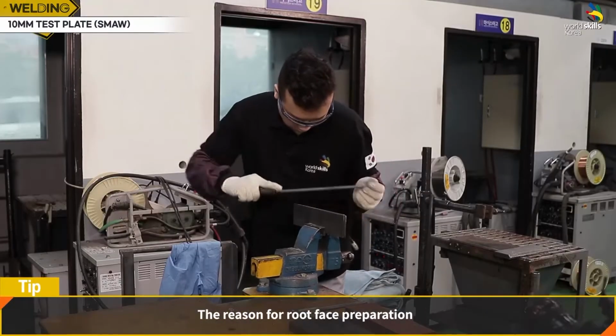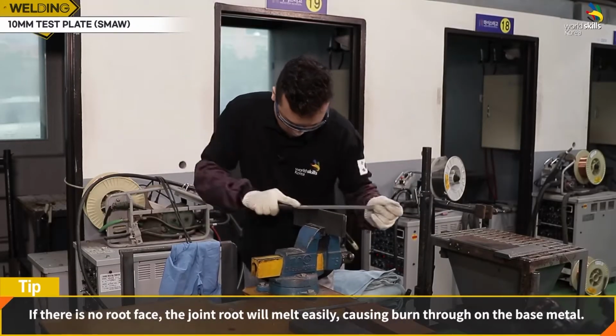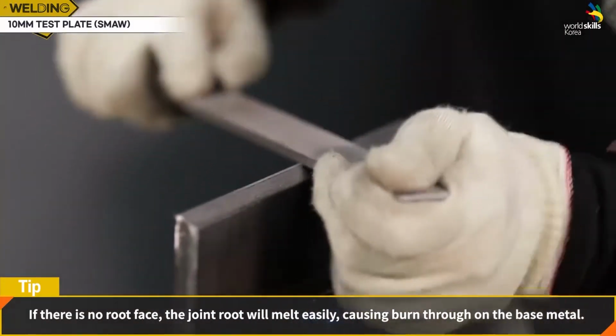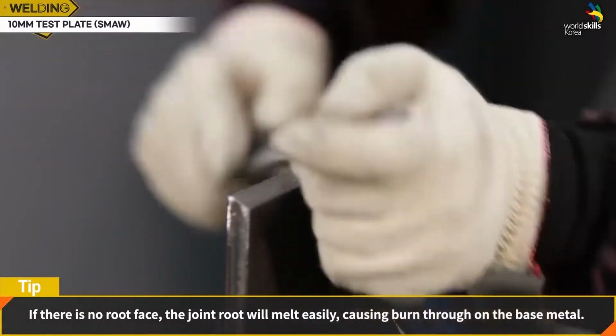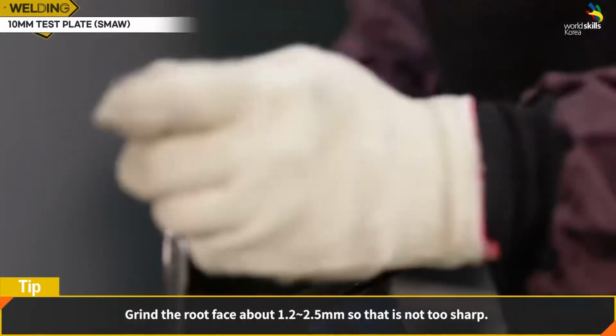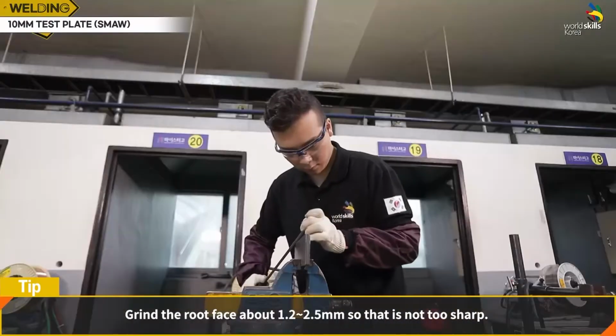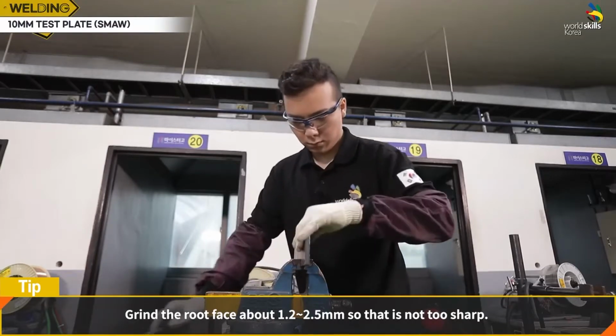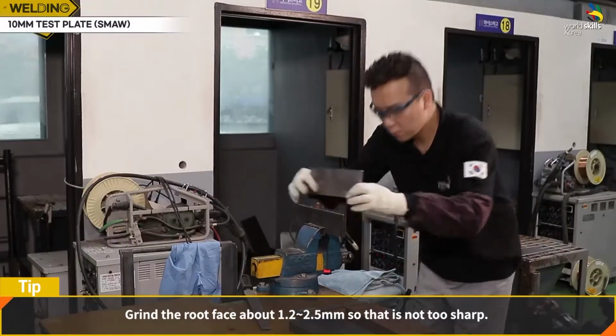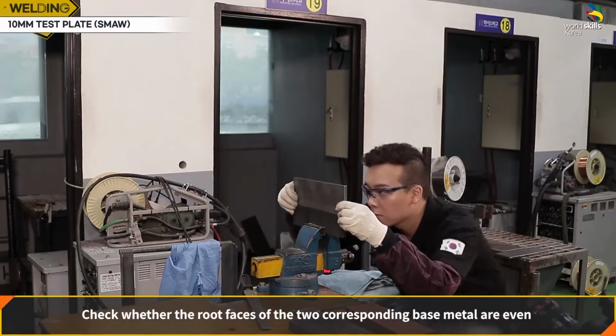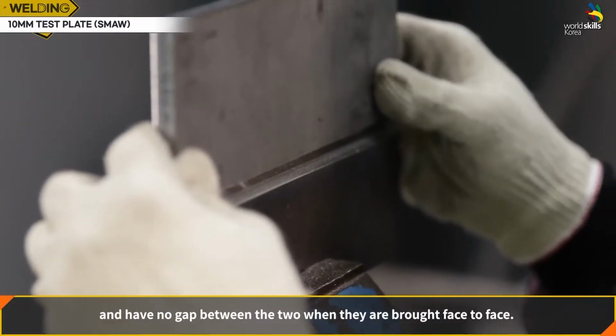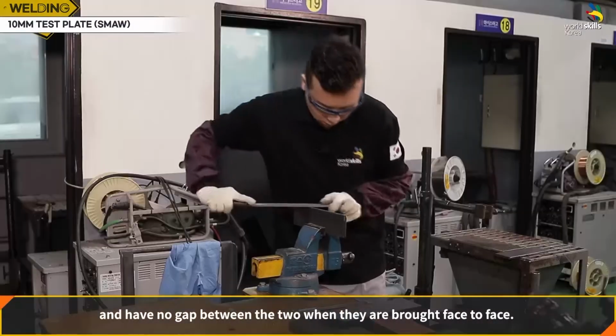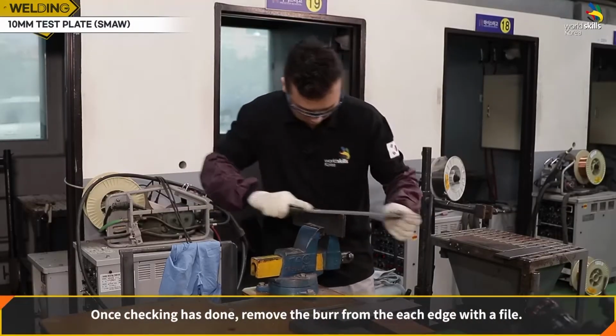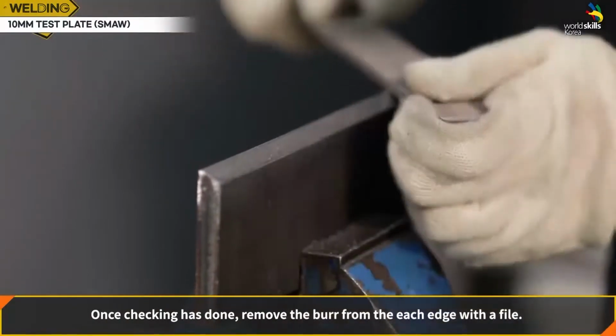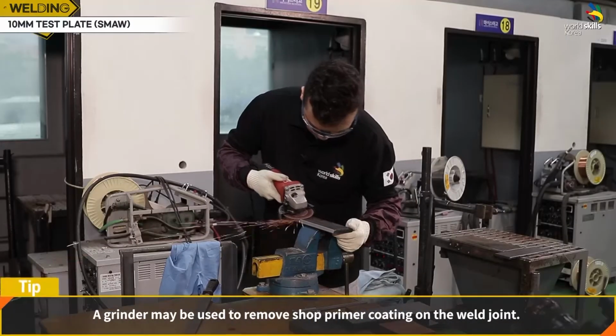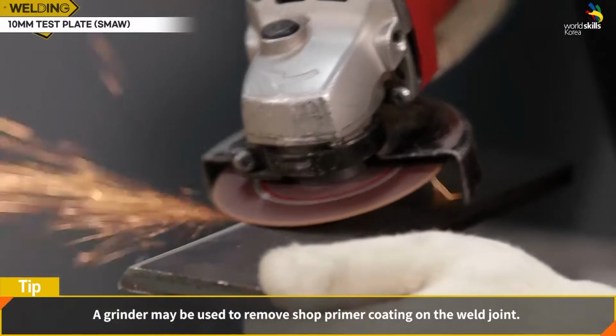The reason for root face preparation: if there is no root face, the joint root will melt easily, causing burn-through on the base material. Grind the root face about 1.2 to 2.5 millimeters so that it is not too sharp. Check whether the root faces of the two corresponding base metals are even and have no gap between the two when they are brought face to face. Once checking is done, remove the burr from each edge with a file. A grinder may be used to remove shop primer coating on the weld joint.